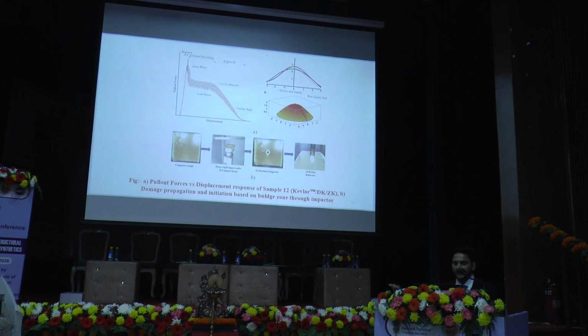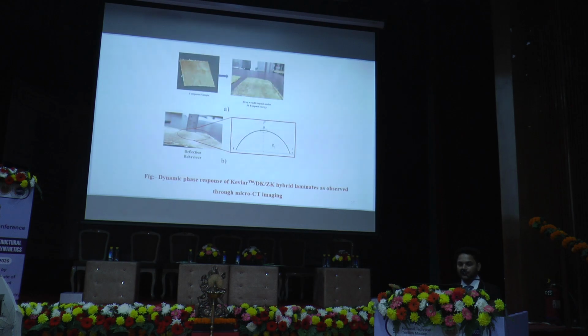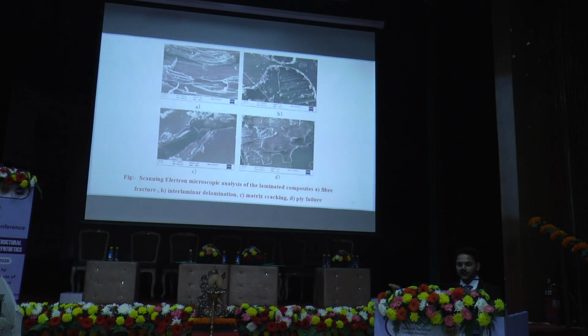As we observed after the impact test, we want to evaluate the bulge zone to know how much impact reaches the helmet skull after this testing. The bulge zone is evaluated according to the scale of deflection behaviors, and we also analyzed microscopically what damage behavior occurs when we impact. Is it damage to the interlayer hybridization of the fiber to matrix interface, or what exactly?